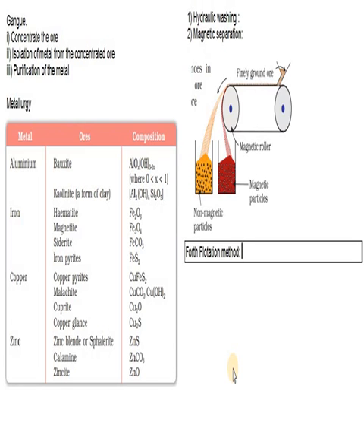They are basically surfactants. Collectors, for example pine oil, fatty acids, xanthates, etc., enhance non-wettability of mineral particles, and froth stabilizers such as cresols, anilines stabilize the froth. The mineral particles become wet by oil, while the gangue particles are wet by water. A rotating paddle agitates the mixture and draws air into it. As a result, froth is formed, which carries the mineral particles. The froth is lighter and is skimmed off, meaning taken out from the surface. It is then dried for recovery of ore particles.